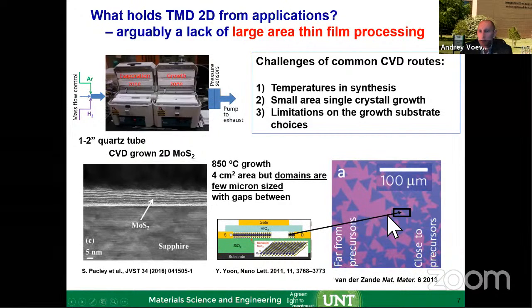Because the danger is that if you just let it go over time until everything is covered, it's also growing the thickness. And once you get the thickness to more than a few monolayers, you start losing all these advantages of the charge confinement. So then all the ideas of why you want to do it disappear.